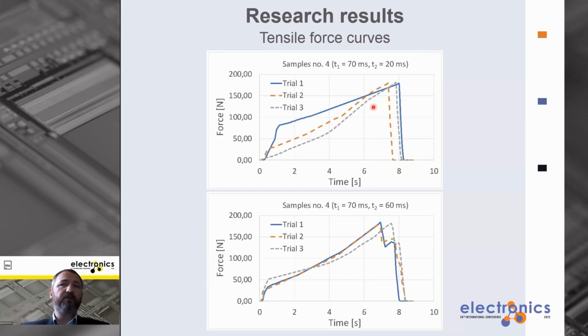Almost always both welds were broken at the same time. But as we can see here, sometimes one of the welds breaks first and then the other. It is due either to an uneven pressing force of both electrodes, or it can also indicate the wear of one of the electrodes. So after adjusting the electrodes, this issue disappears.